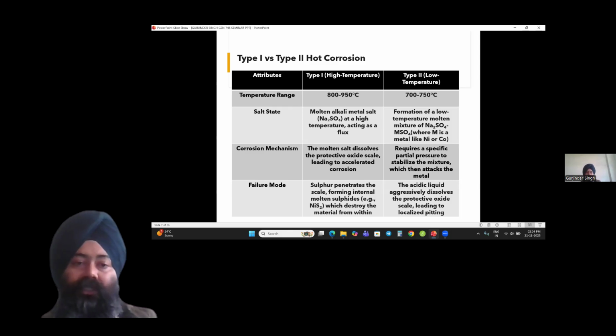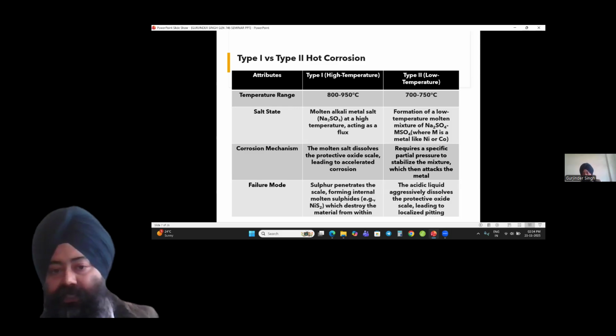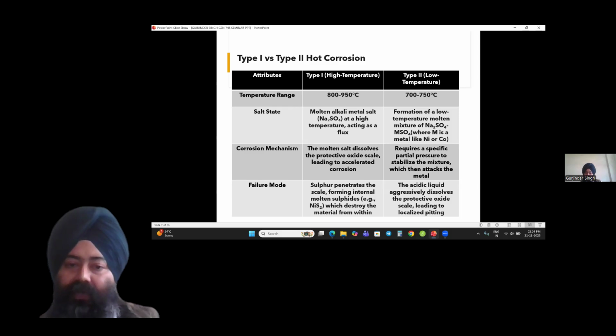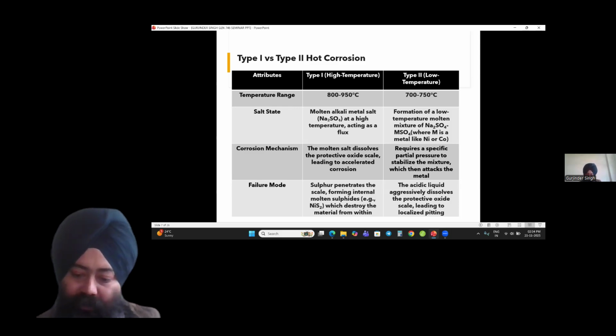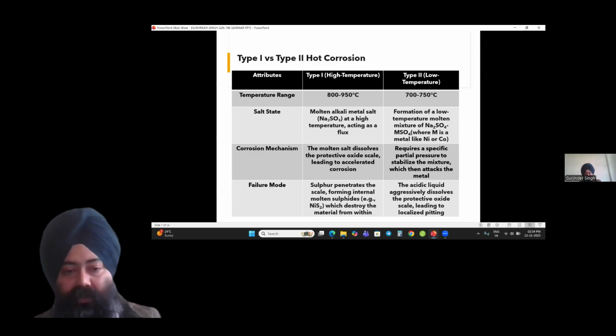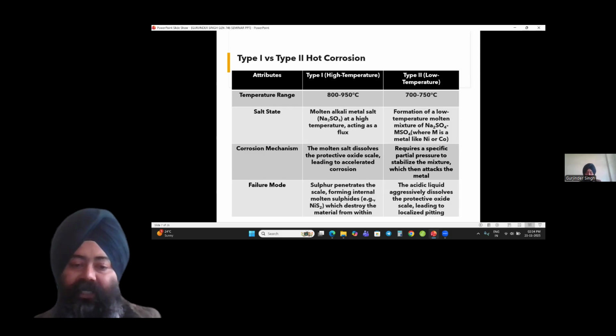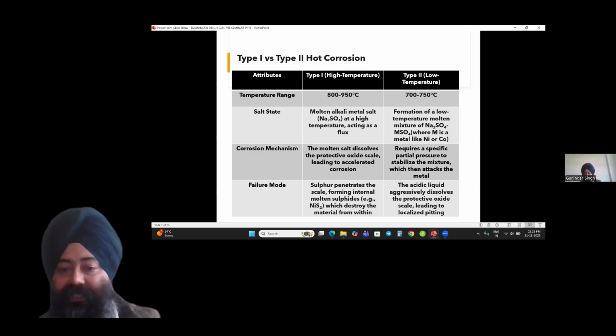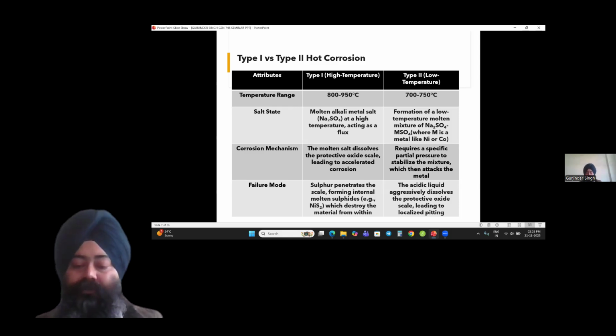What is the corrosion mechanism of both types? In type 1, molten salt basically dissolves the protective oxide scale, as I have discussed earlier in our previous slide, that is, molten salt dissolves the Inconel layer. And in type 2, it applies pressure to stabilize the mixture, and that pressure attacks the metal. What are the failure modes? In type 1, mainly sulfur penetrates the scale, which results in internal molten sulfide, for example, nickel sulfide, which destroys the material. And in type 2, there is an acidic liquid, which dissolves the protective oxide scale, or you can say layer, which leads to localized pitting. That is, there are pits on the surface.